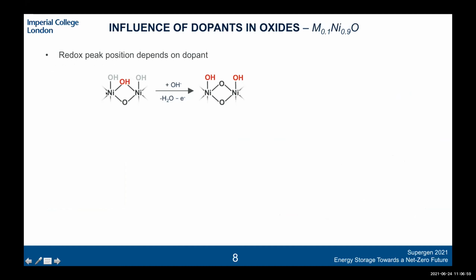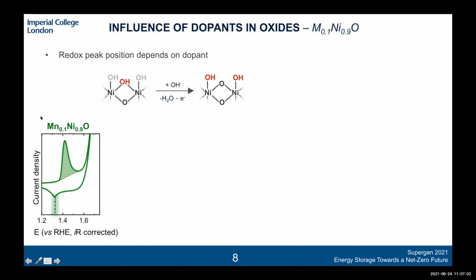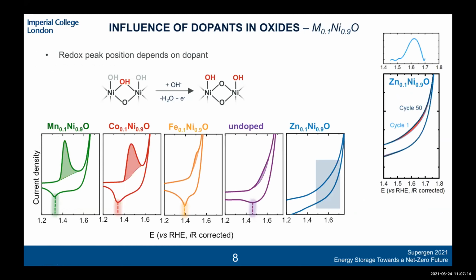And you can see this redox reaction here, specifically in the case of the manganese doped oxide, where you have this really strong redox peak, which is shaded here just prior to this kind of catalytic current. And looking at this redox peak for all the different series of oxides that we've studied, we see that going from the manganese to the zinc doped oxide, the position of this redox peak progressively increases to higher potentials. And what that implies in terms of these materials is that, for example, in the zinc doped case, the binding energy of this oxygen is really weak, and therefore it takes a much higher electrochemical potential to form this oxyhydroxide phase in the case of the zinc doped catalyst.